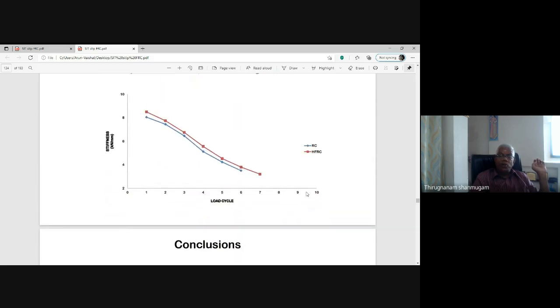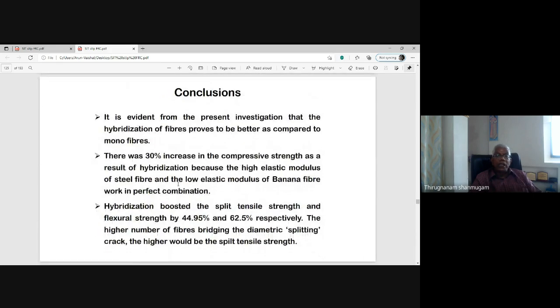Stiffness degradation: both HFRC and RC are exhibiting a similar type of stiffness degradation. You can notice here the vegetable fibers have very low modulus. That is why we are not expecting a sufficient amount of stiffness. Conclusion: there was a 30% increase in compressive strength as a result of hybridization. Hybridization boosts the split tensile strength and flexural strength by 45% and 62% respectively. So the increase in compressive strength is only 30%, whereas the increase in flexural strength is 60%.